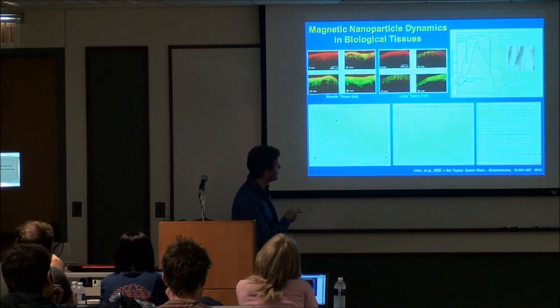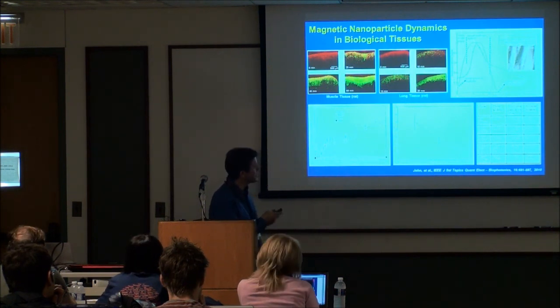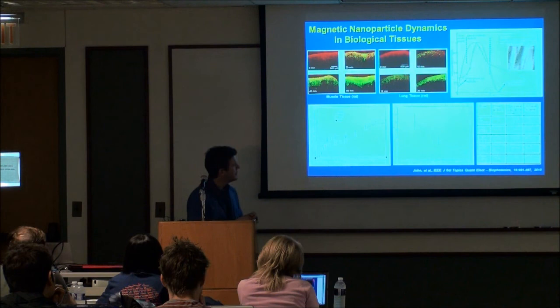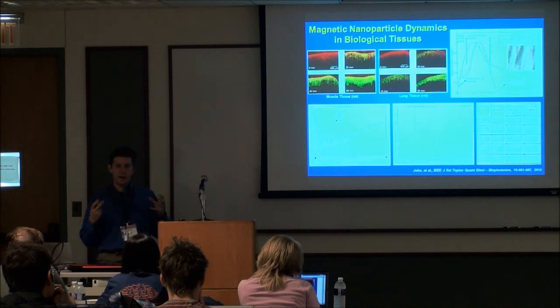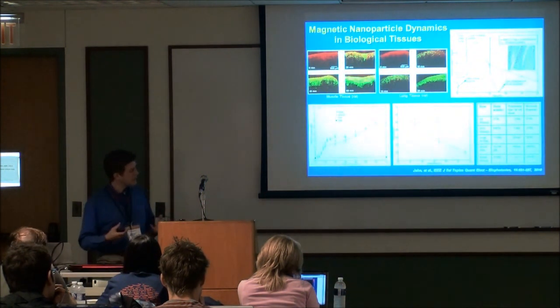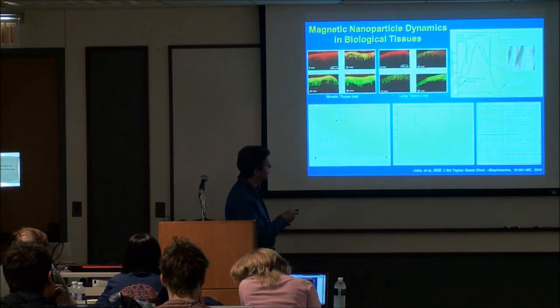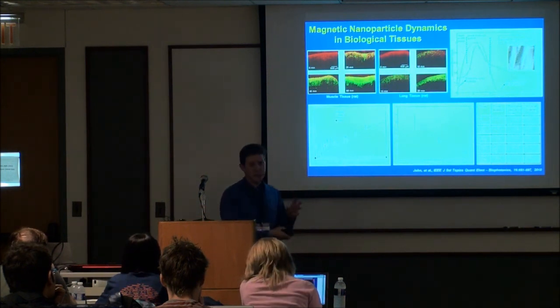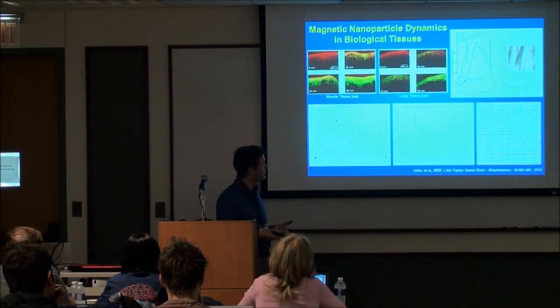So we drew this curve. We hypothesized at first that when we had a sample that had very low viscosity, then we wouldn't see any signal. So what we're plotting here is the normalized magnetomotive signal over time from a gel that's going to be hardening. It starts off as a liquid. We added the different components, and it's going to start to harden over time. So we hypothesized we would see no signal. As that gel becomes sticky and viscoelastic, that signal would go up. And as that gel becomes completely solidified, our signal should go to zero as well, right? Because there's going to be no movement.